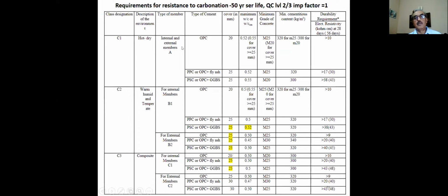For external members, if using OPC, then these are the values of cover, water cement ratios, and minimum cement content you have to maintain. If you're using PPC or OPC with fly ash, then these are the values which you have to use. Similarly, for other conditions, for warm and humid and temperate environment, for internal environment members it's different. For external members, it is stringent.